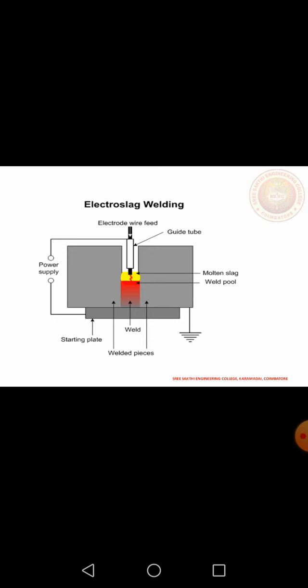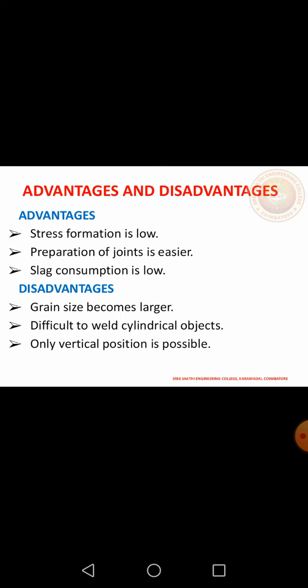As the filler metal solidifies in the weld cavity, the current flows through it. It will generate heat due to electric resistance. This heat is further used for continuous melting of the filler metal into the weld cavity. The filler metal is continuously provided through the roller arrangement as shown in the figure. During the welding, both the copper shoe and feed mechanism move upward until the whole cavity is filled. This will create a strong joint in a single pass. Single or multi-pass weld is used according to plate thickness. The advantages and disadvantages are given below.